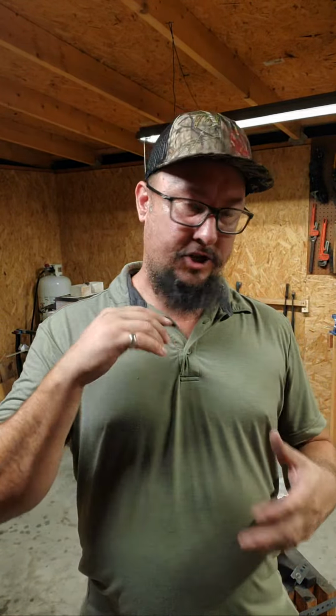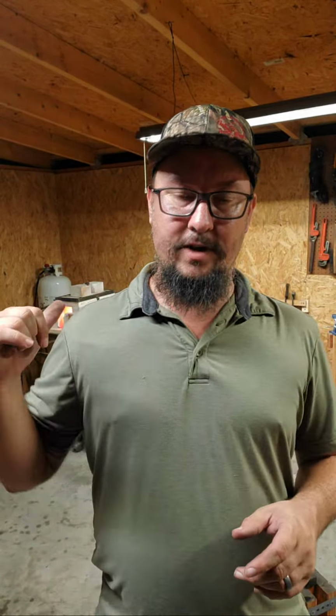I only really need those couple, and just remember, again, different steels require different things. This is 5160. It's one of the most forgiving steels that you will ever mess with. It's a beast to forge, but 5160 is easy. It has a very broad heat treatment process. There are people who have heat treated it, quenching it at 1575 degrees all the way down to 1450 degrees, and they got decent results. A lot of the different spaces in between that. So it's a very forgiving steel.